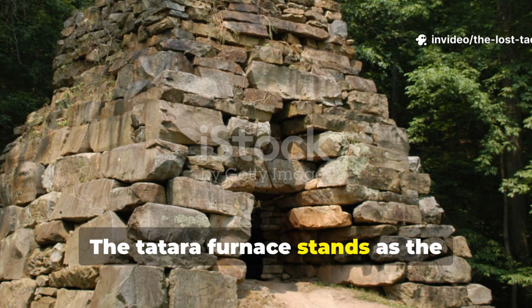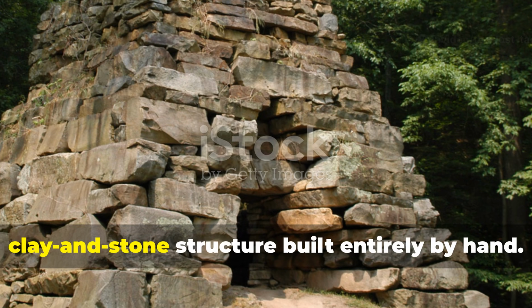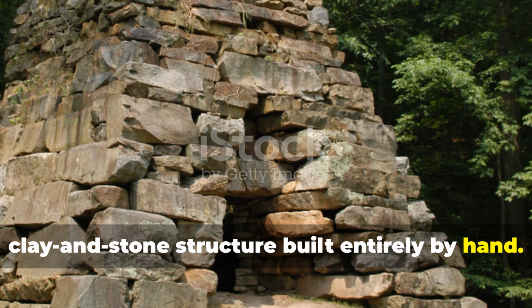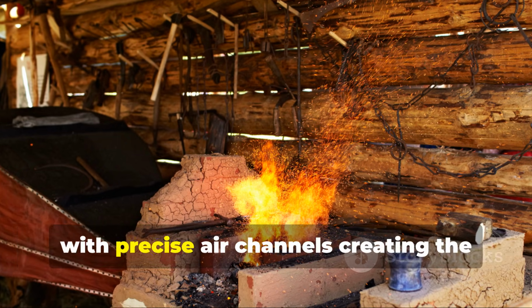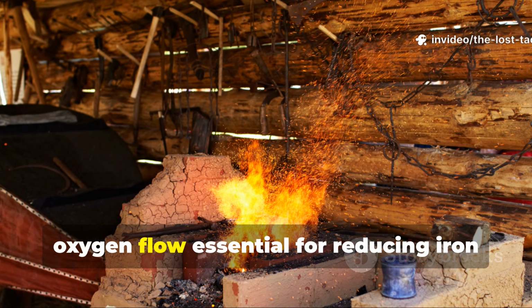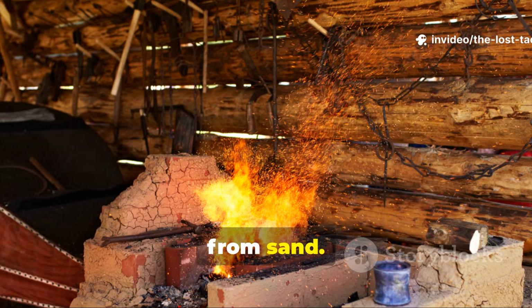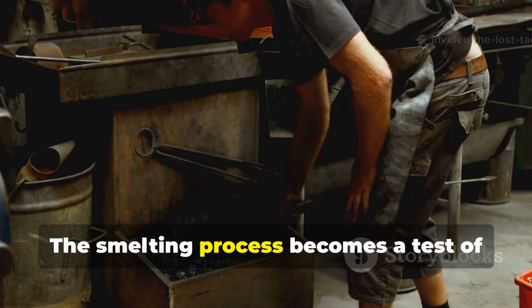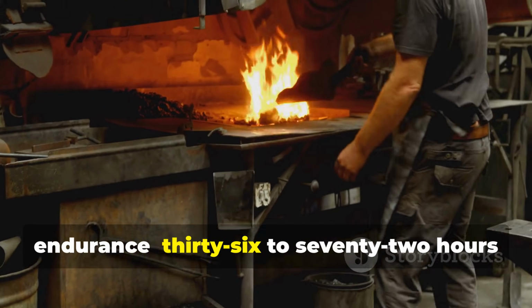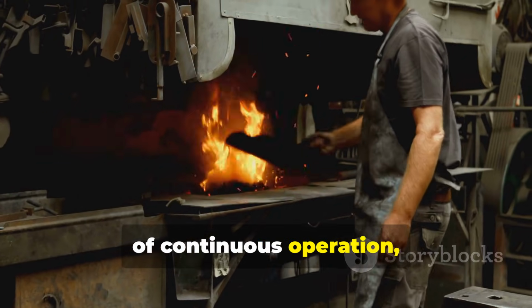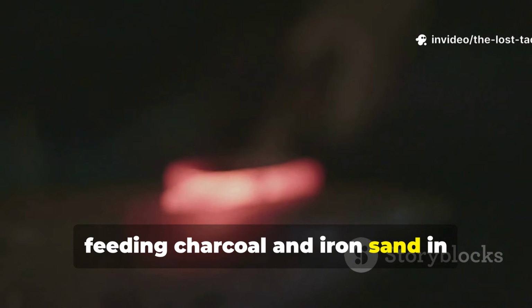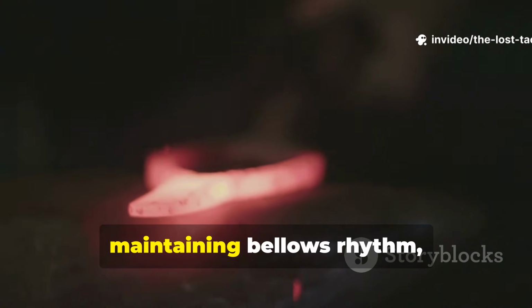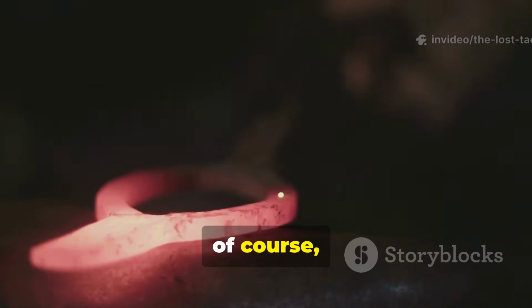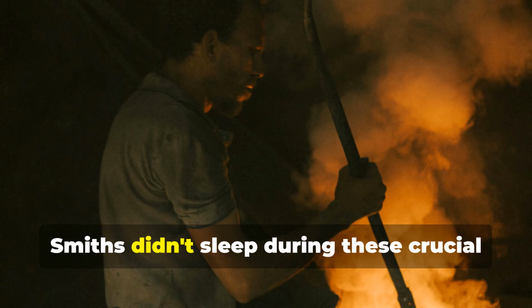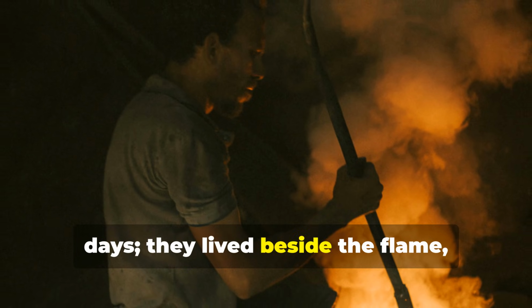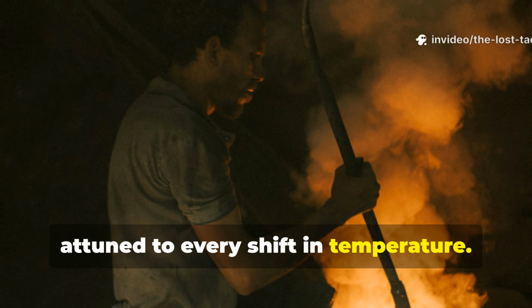The Tatara furnace stands as the cornerstone of our endeavor, a clay and stone structure built entirely by hand. Its construction follows ancient blueprints with precise air channels, creating the oxygen flow essential for reducing iron from sand. The smelting process becomes a test of endurance. 36 to 72 hours of continuous operation, feeding charcoal and iron sand in measured intervals, maintaining bellows rhythm, and, of course, monitoring the furnace's breathing. Smiths didn't sleep during these crucial days. They lived beside the flame, attuned to every shift in temperature.